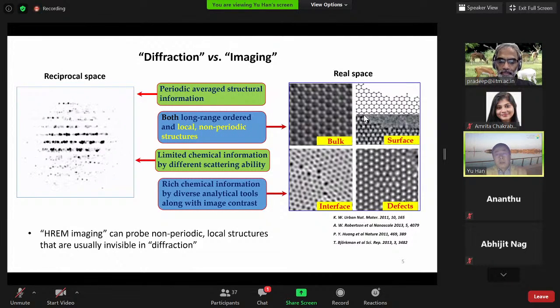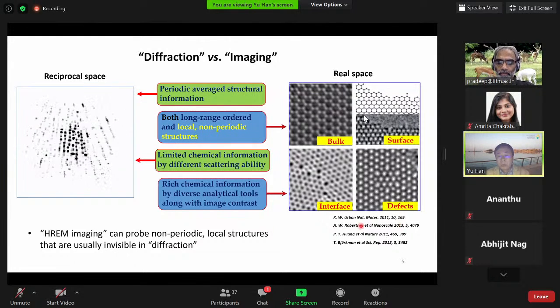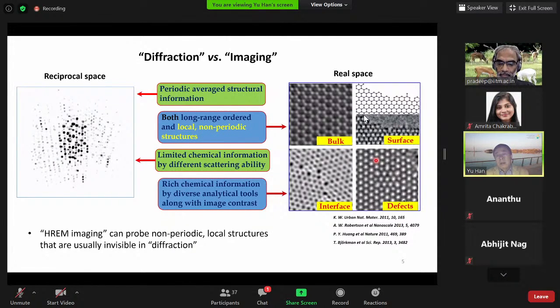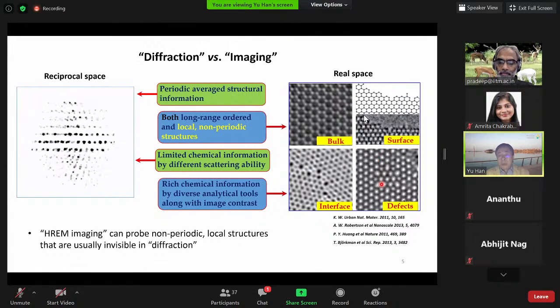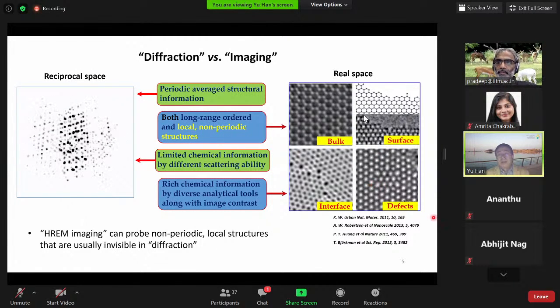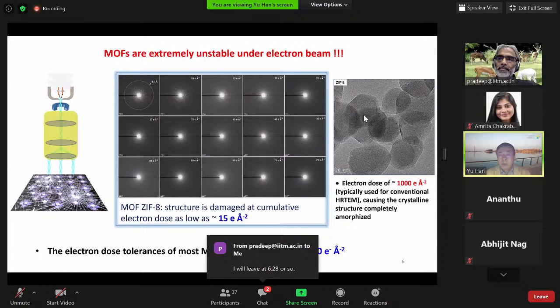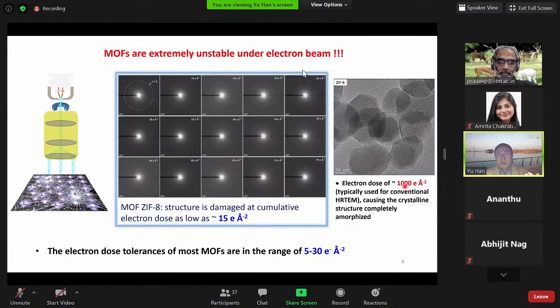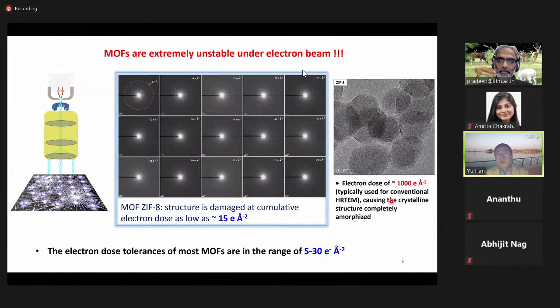As I mentioned earlier, HRTEM is a good choice for probing the local structure, right? But MOFs are extremely sensitive to the electron beam, and they cannot be investigated by conventional HRTEM. So here I give you one example to explain this problem, the so-called beam sensitivity problem. Here you see a TEM image of a MOF called ZIF-8, okay? And this image was acquired with an electron dose of about 1,000 electrons per square angstrom, which is a very typical electron dose used for conventional HRTEM.